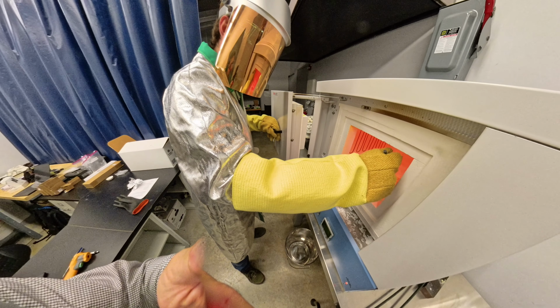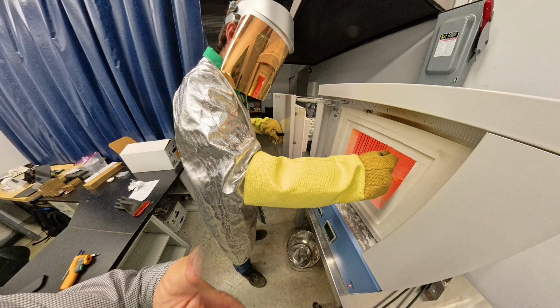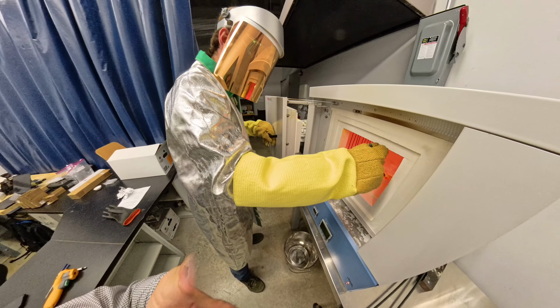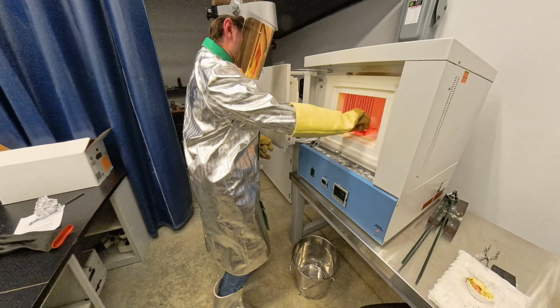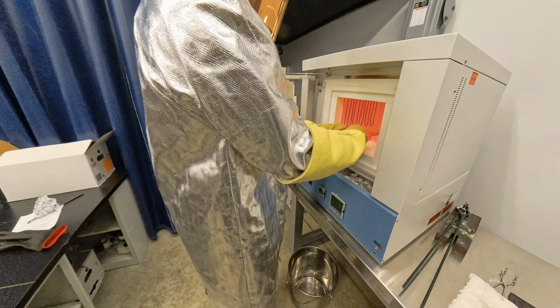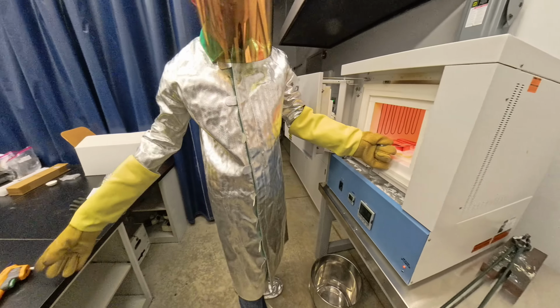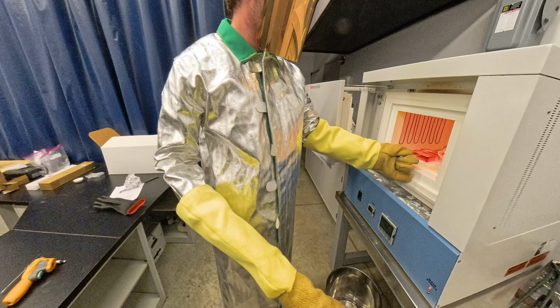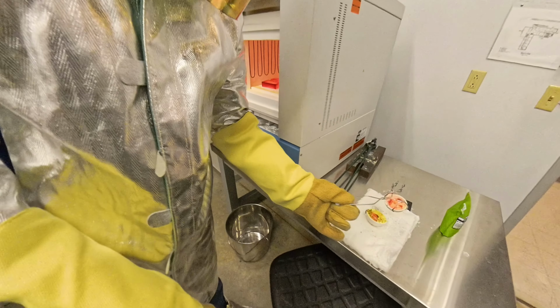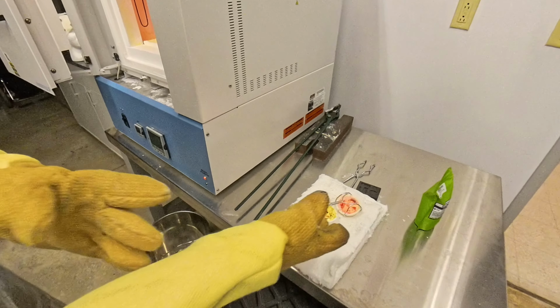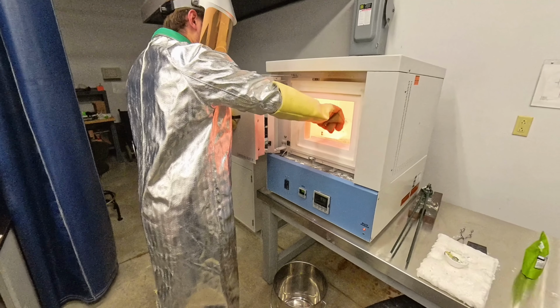I held the mixture at 890 degrees Celsius for about half an hour, mixing it halfway through, and then decided to increase the temperature and leave it there for a little bit longer, and then I tried pouring it out. But as I said so eloquently in this video, yeah, it's not really working at all. No. So, since I still had another one in the furnace, I increased the temp to a little over 1,000 degrees Celsius and let it melt for a couple minutes.